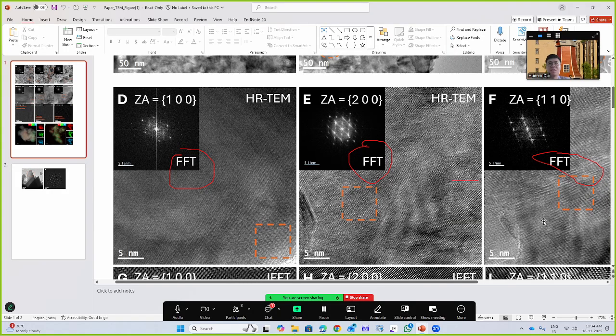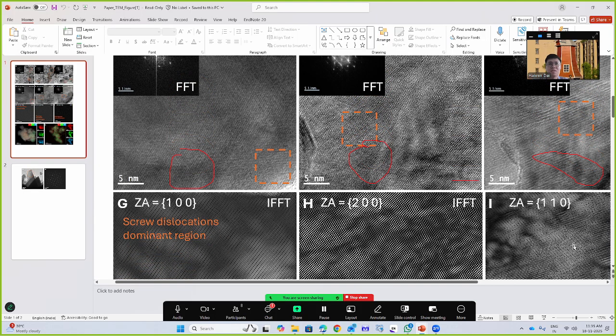structure resolution at this scale is still very challenging. It also doesn't make sense to do so because maybe each of the small grains is slightly different. That's my interpretation. Of course, I can fit it to one of the zone axes forcefully. The position still matches, but the intensity doesn't. In reality, both of them can fit, but not fitting well. So that is what the high resolution TEM and the FFT are telling us.